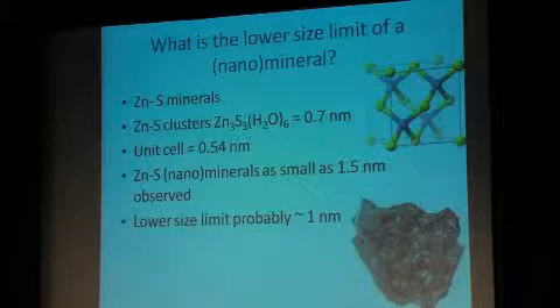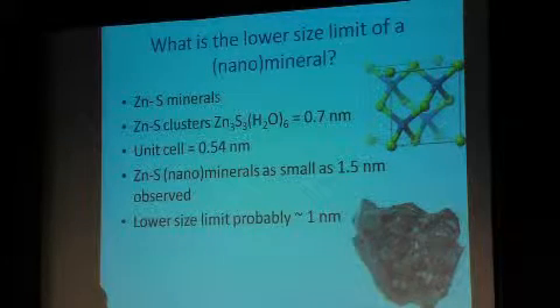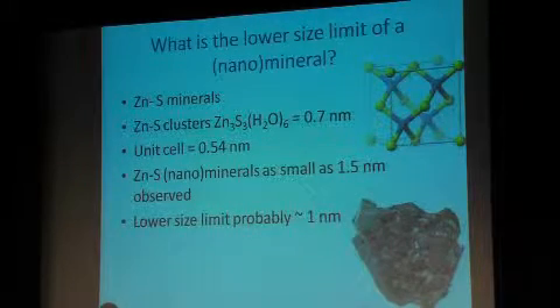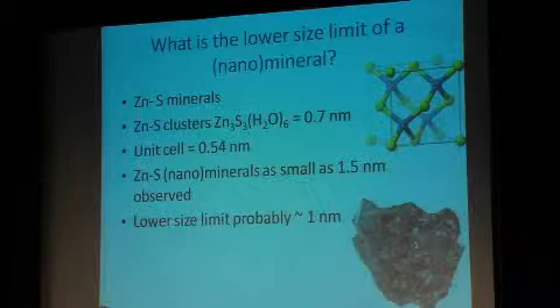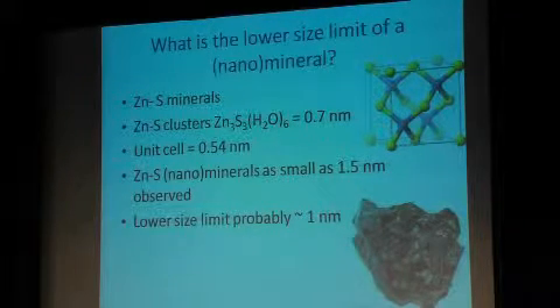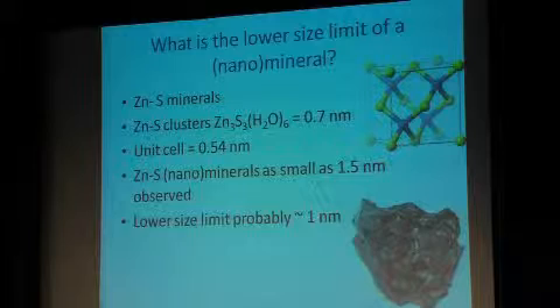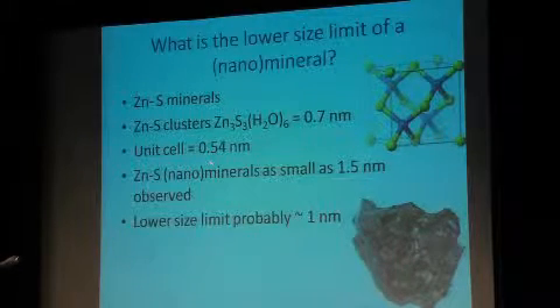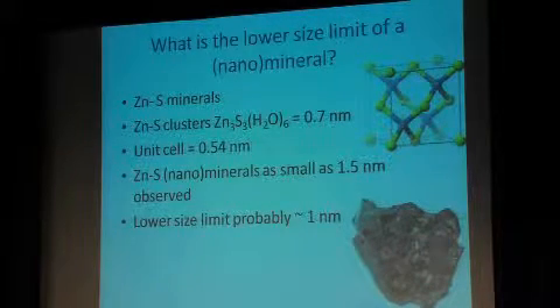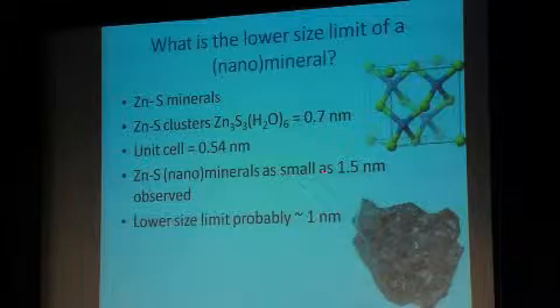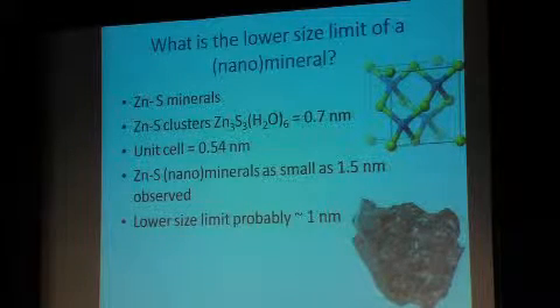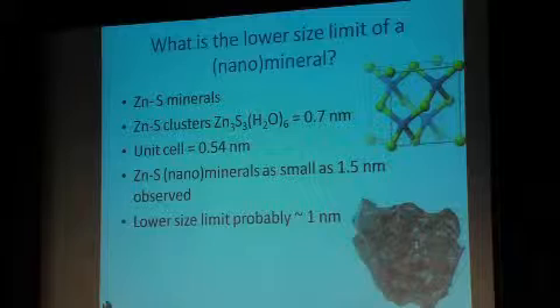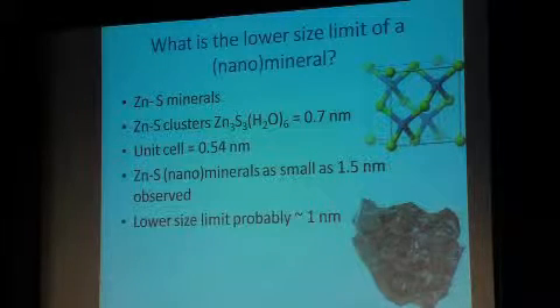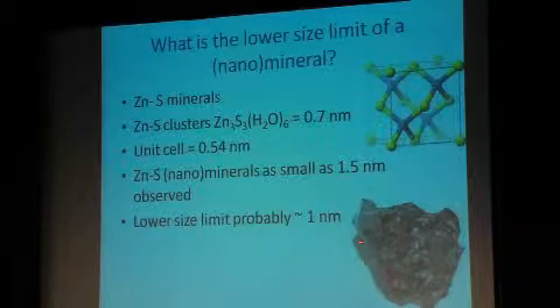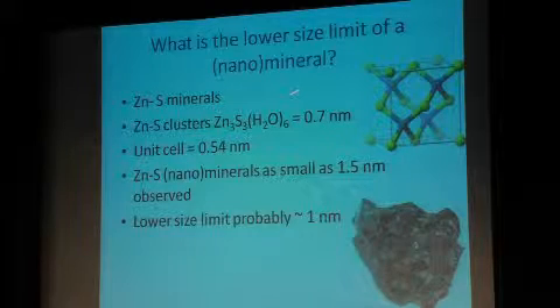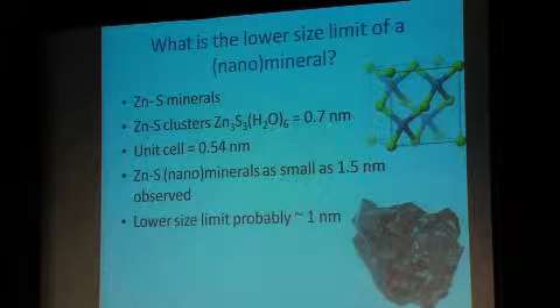In order for something to be called a mineral, it has to have a repeating structure. So you have to have more than one unit cell. So the size has to be bigger than this and probably bigger than this. Zinc sulfide nanominerals as small as 1.5 nanometers have been observed and characterized, and we know they have a crystalline structure. So what this tells us is that the lower size limit for something to be called a nanomineral is probably about 1 nanometer.